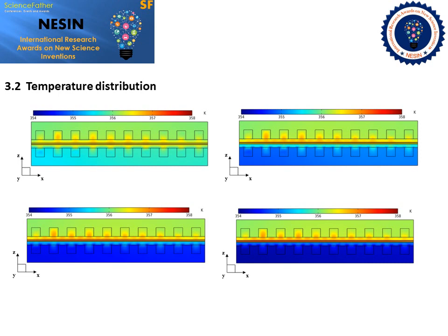The temperature of the cross section shows a trend of differences in all directions centered on the cathode cell, and the temperature difference trend is strong in the range of the cross section close to the gas inlet, and gradually decreases in the part of the cross section far from the inlet.